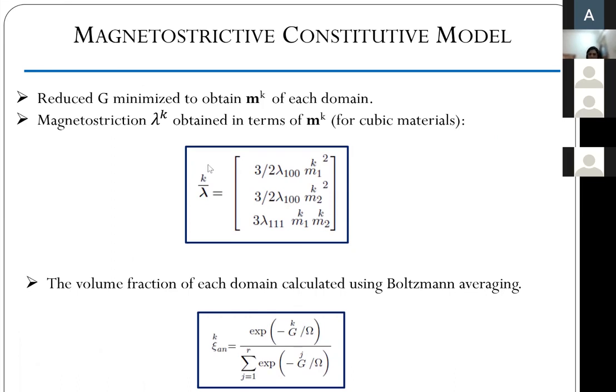For a cubic crystal, magnetostriction, I have only written the 2D components here, so this is what we get. Then we get the magnetic moment orientation within each domain, and we calculate the volume fraction of each domain. If we remember correctly, for a certain applied magnetic field, some domains grow, right? So the volume fraction occupied by certain domains will be larger compared to some others. That is calculated using statistical mechanics.